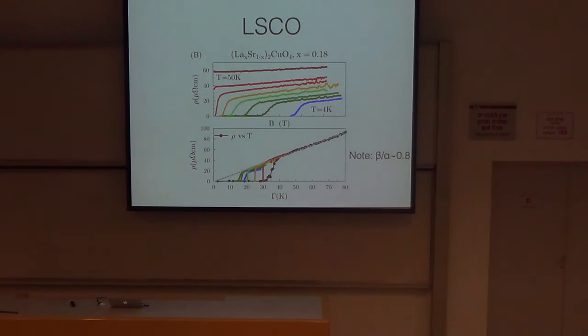Again, apart from perhaps the very lowest temperatures, where it's possible you're crossing over into one of the energy scales, for most of the curves, and these are just the same data with no offsets, just plotted in a different way, they all seem to approach this T-linear line that you're familiar with from the zero field behavior. So it's remarkable. I hope it's correct, but it's certainly true from the data. Whether this is the correct interpretation is one matter, but the data certainly does have this kind of scale.